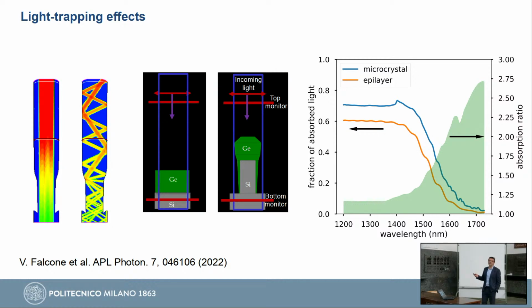If you have an inclined facet and a high refractive index material like germanium or silicon, when light comes and hits this inclined facet, it will be trapped inside. While if it comes on a flat part, it will go straight through your layer. So it's clear that now the optical path, and so the possibility of being absorbed for a photon, is much higher in this case than in the other. So we can expect that if I calculate the absorption of a faceted crystal over one of a flat area, I would get a larger absorption.